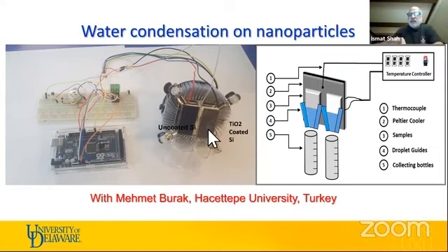When you cool it down, and again, it requires very little energy, that all can be obtained from a very cheap, dirt cheap solar cell. So totally independent product. And you can collect a lot more water on a titanium dioxide coated silicon than you can through uncoated silicon. And this is part of the work that I was supposed to finish this summer, but unfortunately I didn't get to go, but I will eventually end up there and finish this off.